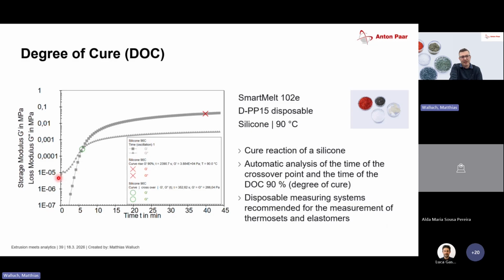And we see here in the beginning, G' is something here below, G'' is here. This means the material is behaving like a liquid. And the longer we keep the material at the temperature, the material starts to change. And here we see G' is going up and up and up, and here we have a crossover point. This crossover point is important because this is the gel point. From this point on to the right side, we see that the material is getting more and more solid. And here, in the end, we get a plateau, and here the material is 90% cured, I would say. And if we have different material formulations and different temperatures, of course, the shape of the curves will change.